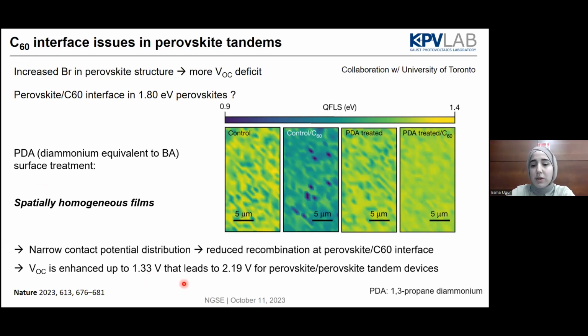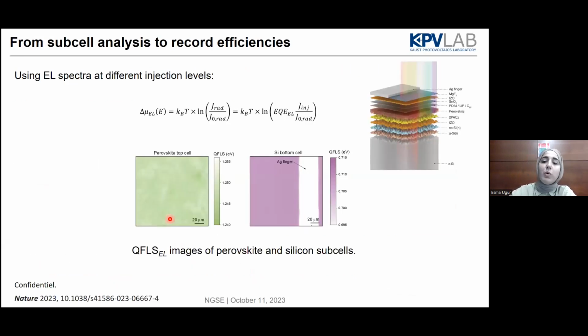So this was the perovskite tandem that was helping a lot with the open circuit voltage for these devices, but it is also working in the perovskite silicon tandems that have a 1.68 eV perovskite. For these ones, we were also working on the subcell analysis, as I mentioned, where we can do electroluminescence measurements. From the same spot of the device, we can selectively get the emission from the perovskite that you can see here, or the silicon.